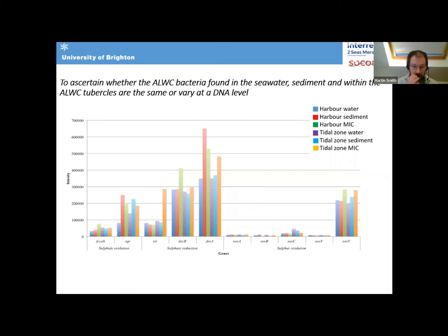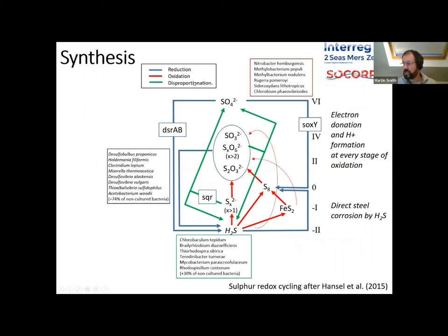So coupling that with 16S RNA analysis to identify the bacterial species, we can put together an idea of what the sulfur cycling processes are going on in this corrosion material. So the central diagram here is from Hansel 2015. It summarizes the cycling between sulfate and bisulfide and the intermediate oxidation states that are going on in there. In the boxes around it and labeled with the gene activity, we can now say within a single corrosion sample, we have sulfate reduction going on, we have microbially mediated sulfur oxidation going on, and we have disproportionation.